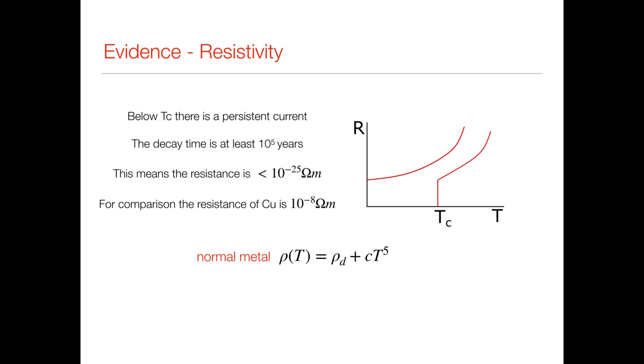This means, on the basis of experimental limits to how accurately you can actually measure a current, the decay time is at least the order of 10 to the 5 years. That's really quite a long time. So the resistance, if it isn't exactly zero, is extremely close to zero. Within experimental error, we think the resistivity is less than, say, 10 to the -25 ohm meters. Just for comparison, copper is considered to be a good metal, and the resistivity of copper is about 10 to the -8 ohm meters. So we've got many orders of magnitude difference.